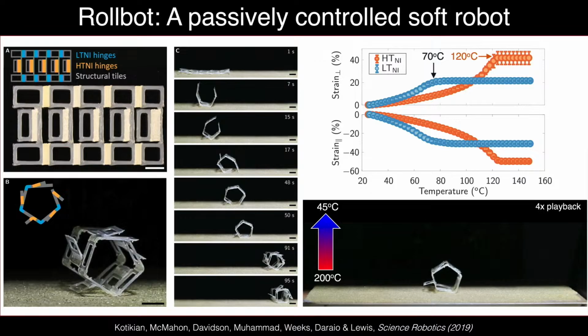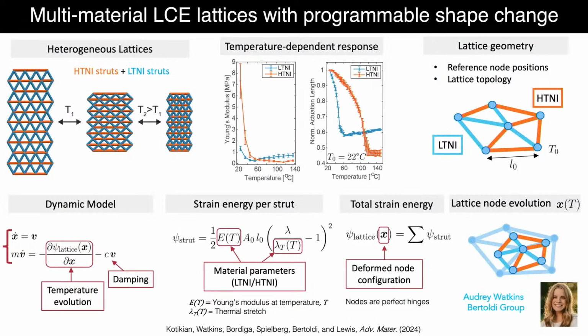What I want to show next is a little bit of back to lattices. And here I would say that we again take advantage of the fact that we have these two disparate LCEs. We can encode in their director alignment along these printed either diagonal struts or horizontal struts. And by mixing and matching where the high TNI and low TNI struts reside, we can really change the way in which these architectures shape morph, and I'll demonstrate that for you in a minute.